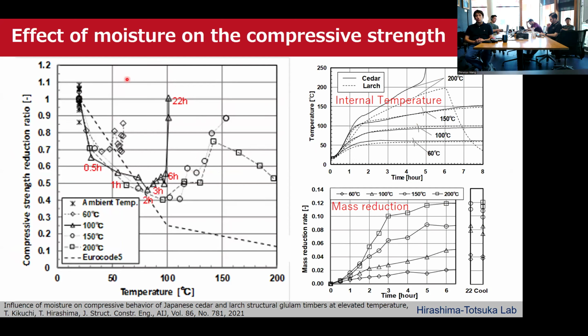This figure shows the relationship between compressive strength and the internal temperature of the specimen. In this figure, the results for 100 degrees also include information on the heating time. When heated to a heater temperature of 100 degrees, the compressive strength was the lowest after 2 hours, and then recovered. The reason for this is thought to be that water remained inside after 2 hours.